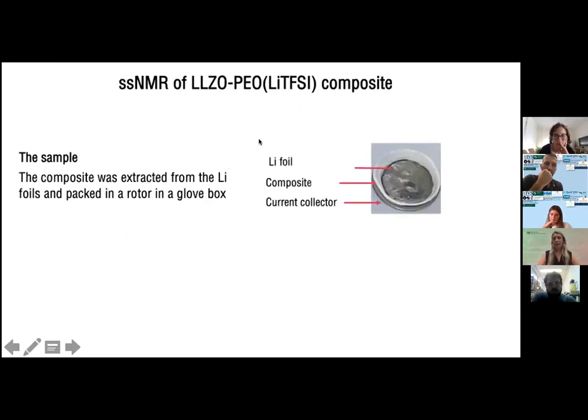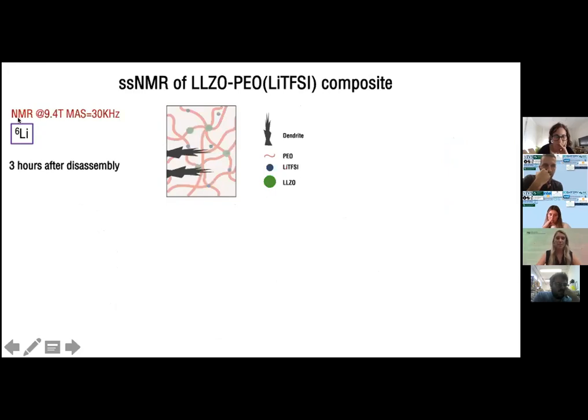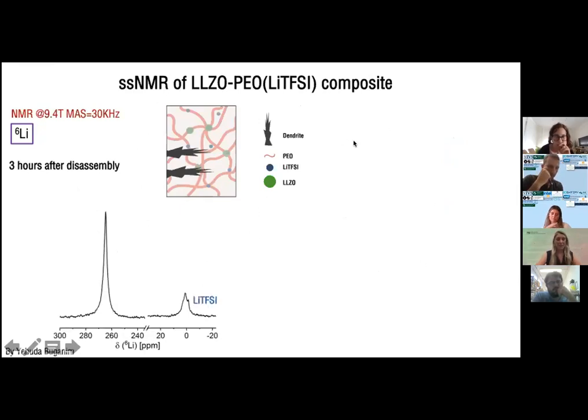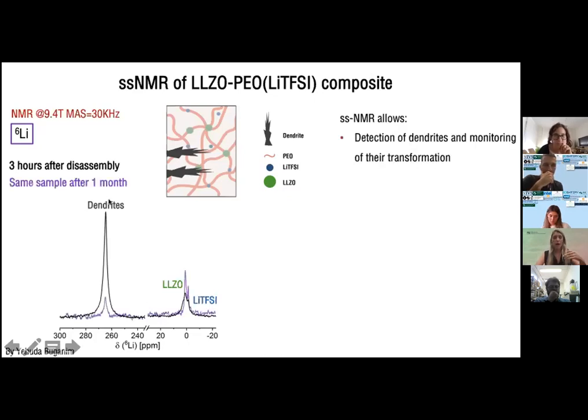So then we took our sample to NMR. We disassembled it, we needed to extract the composites from the lithium, and we packed it in the rotor, which is the sample holder for NMR, in a glove box, of course. And we took a lithium-6 NMR spectrum 3 hours after the disassembly. This is, once again, the representative of our cell. And you can see here, we clearly see the lithium TFSI, the LLZO peak, and lithium metal, which is our dendrites. We took another measurement of the same sample after 1 month, and we can see how the dendrite signal dropped